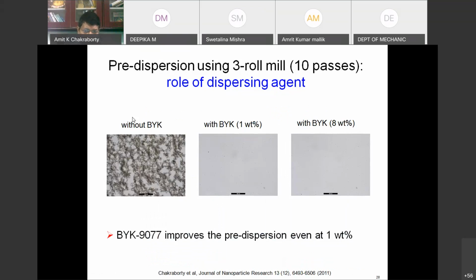You see that some dark particles are there in the left-hand figure. The middle figure has no particles because we have used 1 weight% of BYK. So we see there is a strong influence of this BYK surfactant in improving the dispersion. Another try we did with a larger amount of BYK, 8%, is also very good. But we cannot use very much because these surfactants are basically soft materials. If you use too much, they soften the material and your mechanical property will degrade rather than improve.